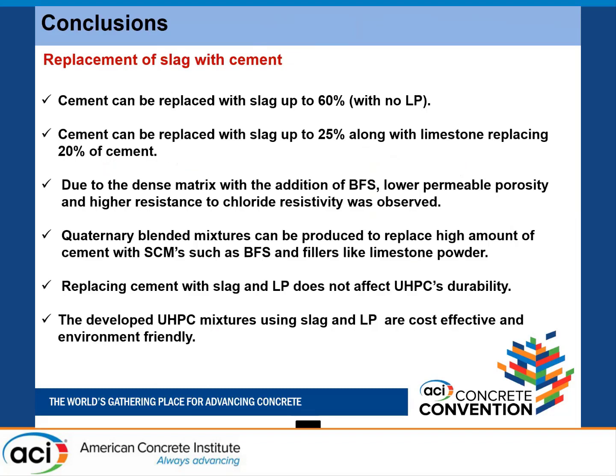And then finally, cement can be safely replaced with slag in UHPC systems up to 60%. If you want to use slag in combination with limestone powder, 25% slag, and you can use limestone powder up to 20%. This combination actually improves the density of the concrete too, resulting in very low permeable porosity and very high resistance to chloride penetration, we observed.